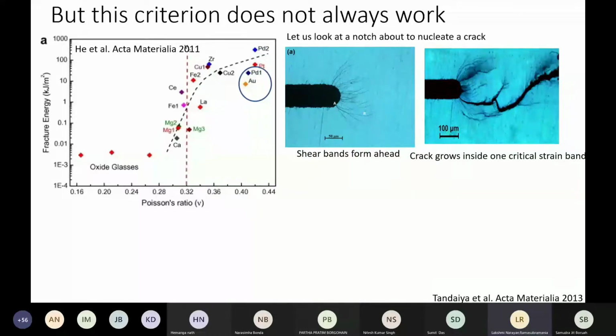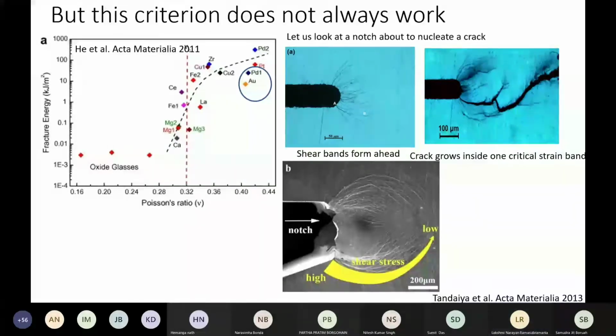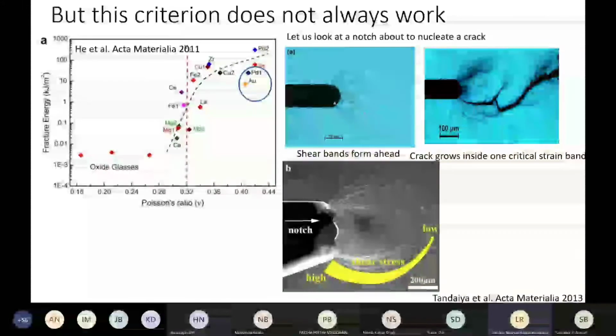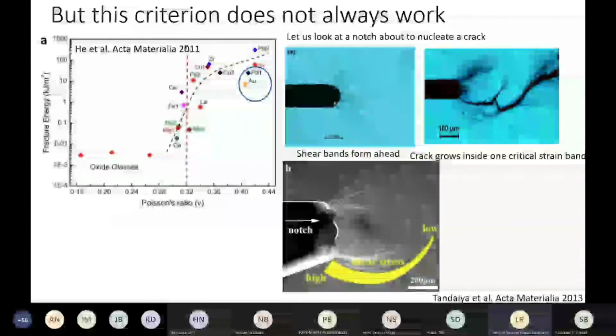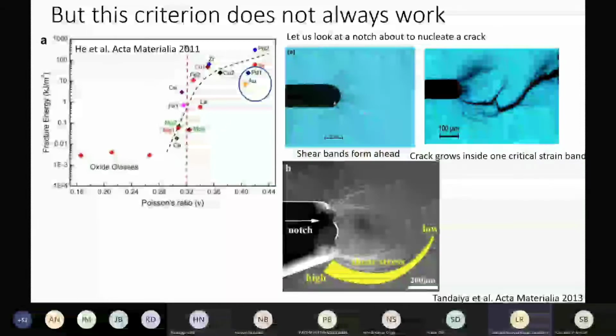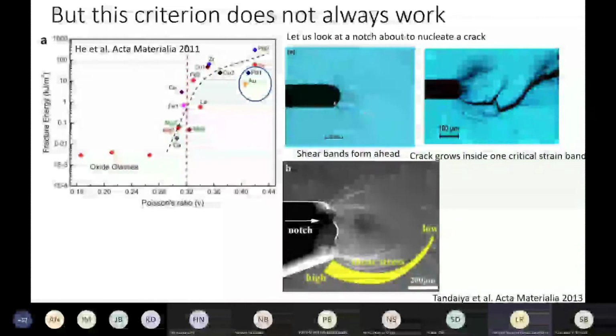So then it was found by several researchers. In fact, Parag, who actually is a faculty in IIT Bombay, came up with this criterion that a critical strain has to be reached within this shear band for this to nucleate a crack. And that critical strain was given as 10%. Okay. And this is followed for all metallic glass systems. You will see that shear bands form in front of a notch, and then within the shear bands, you can always form a crack. And this kind of a shear band envelope forms in them. This is very unique to metallic glasses. You will never see them in crystalline metals.